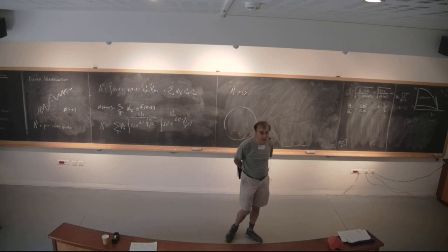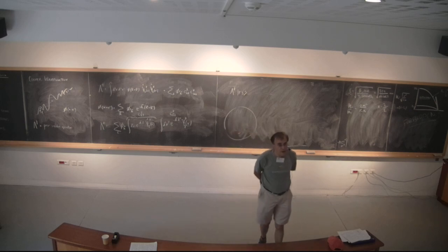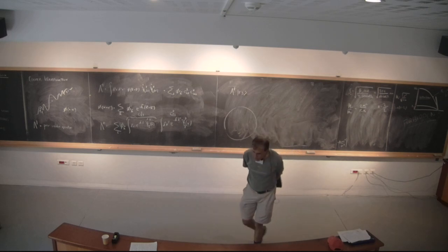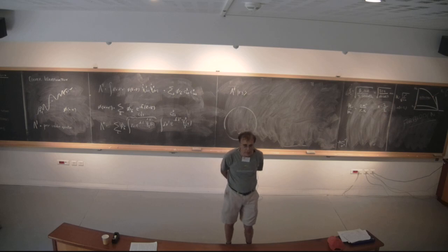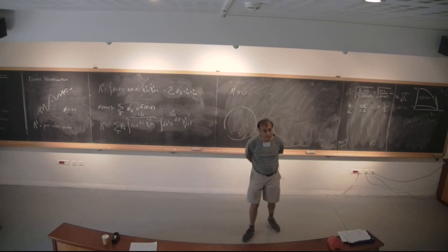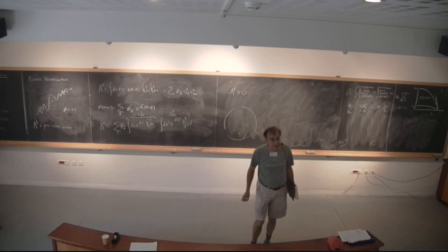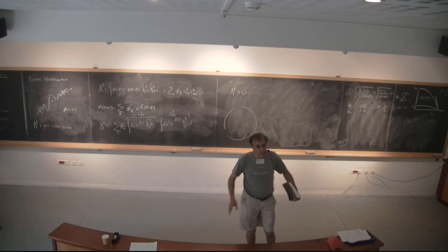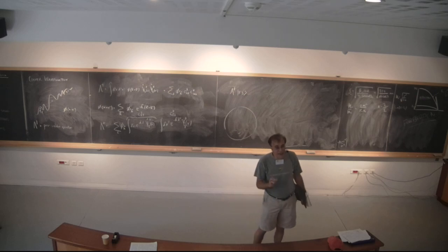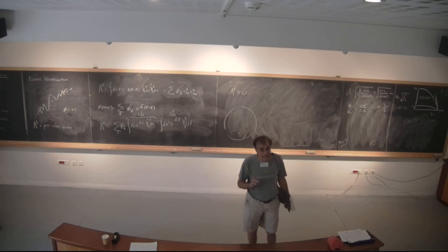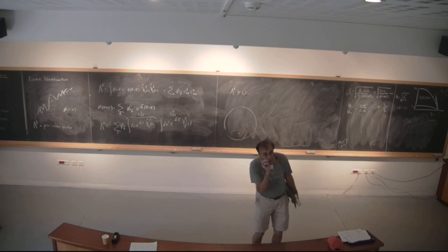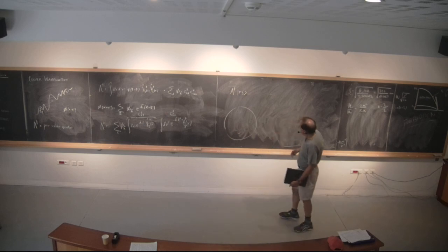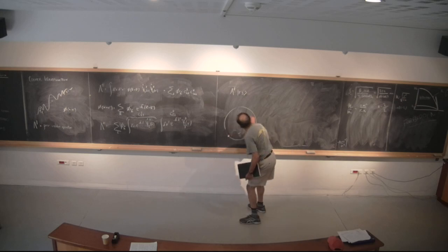So there is a so-called Ginsburg criterion for when the fluctuations are important, and that criterion, which is not in my head at the moment, basically when you work it out in superconductors gives you an extremely narrow region around Tc. So if you look at the specific heat capacity of helium-4, it has this great big lambda peak. The specific heat capacity of a superconductor actually has exactly the same lambda peak, but to see the lambda, you have to go so close to Tc, you never see it. Okay, good question.